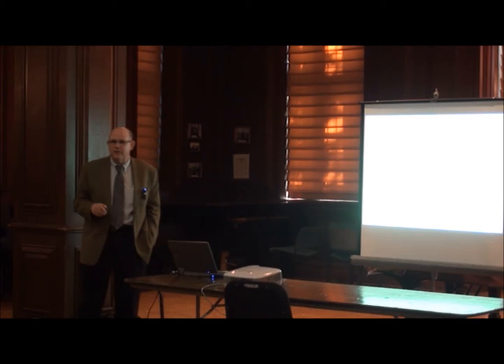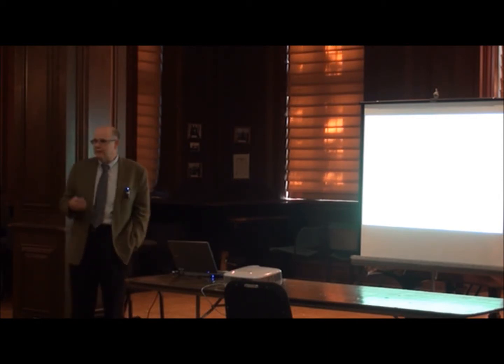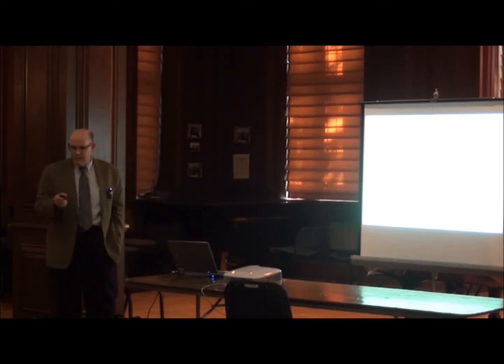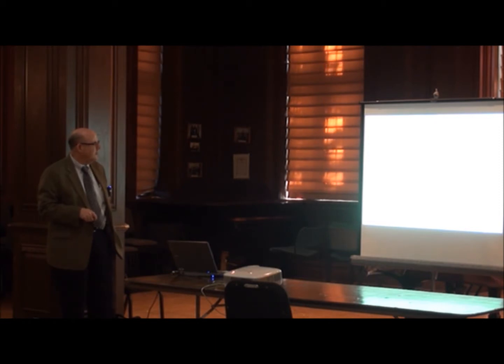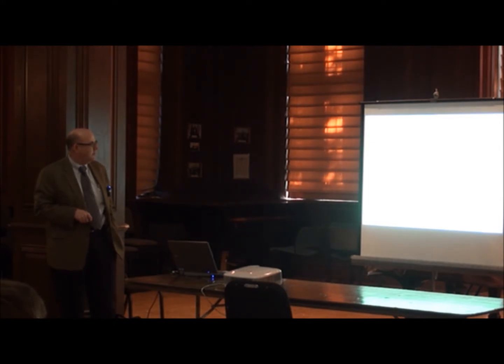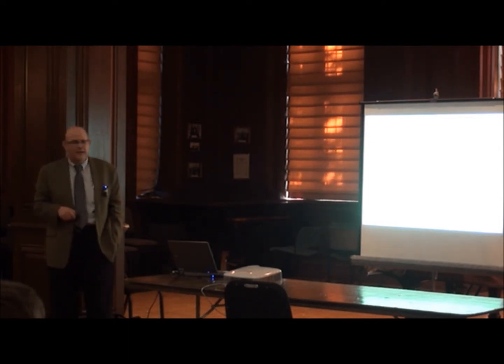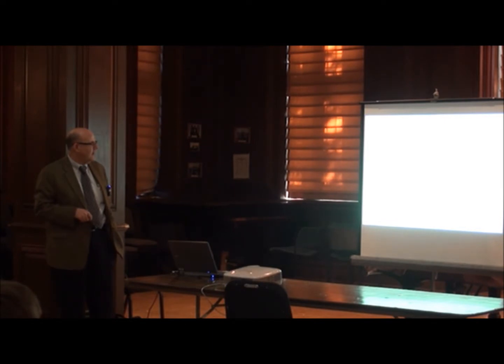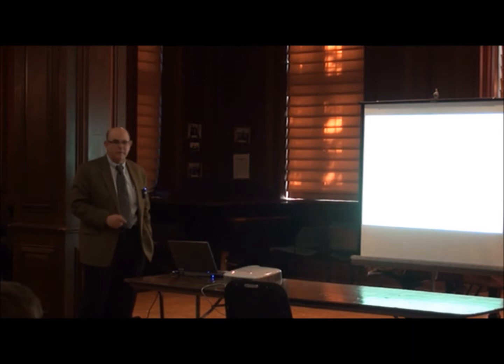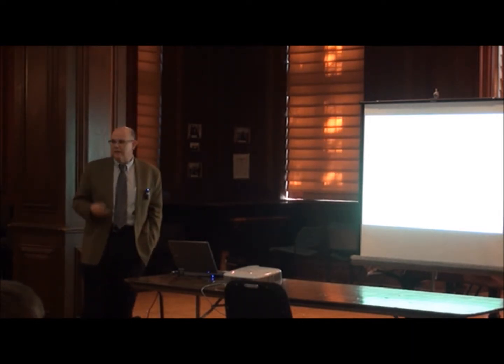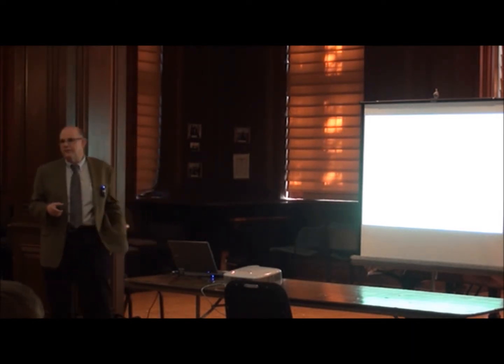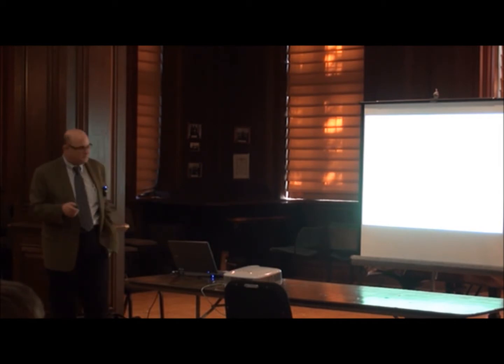As the literature advanced over the years, there are plasticity indices for different types of materials and so forth. But basically, it's a term that looks kind of familiar. It depends upon this effective modulus and now the hardness of the material, and then parameters related to the surface roughness. And let's just look at this. It says physically, if you have a really small hardness, the plasticity number will be large. So basically, a large plasticity number relates to a surface that's going to be plastically deforming.